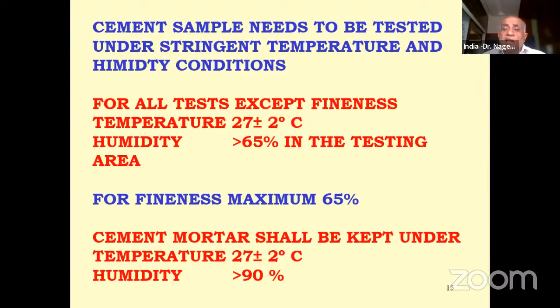Otherwise, the results of fineness get affected. So for all other tests except fineness, the humidity should be more than 65%, and for finding out the fineness of cement, the humidity shall be less than 65%. So cement mortar shall be kept at a temperature of 27 plus or minus 2. After casting the cement, why do we cast cement mortar? What is cement mortar? Cement and standard sand. Standard sand is obtained from Ennore in Tamil Nadu. This is used to check the compressive strength of cement.